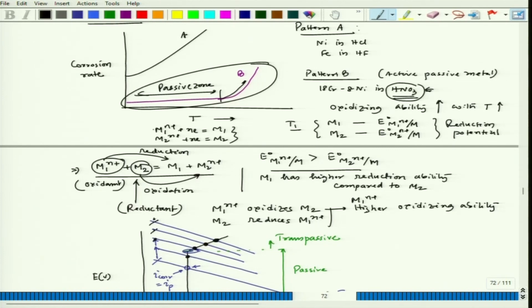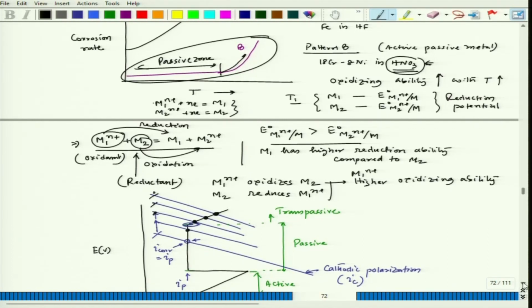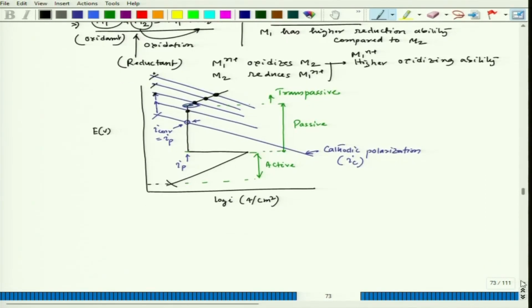So, this is typical of 18-8 stainless steel in HNO3. This is the effect of increasing oxidizing ability of the corrosive with increase in temperature. So, that means we could see two aspects. One is ever-increasing corrosion rate with temperature, and this happens in the case of active metal, since the reaction rate also increases with temperature.